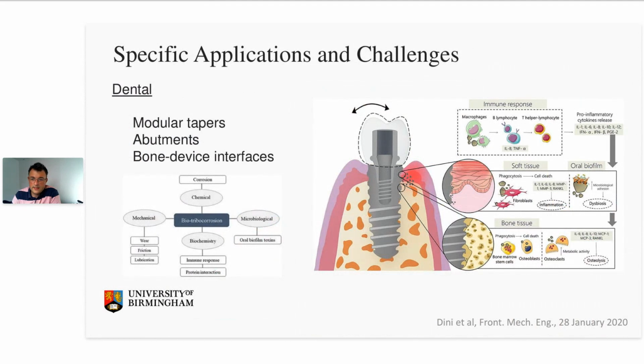A similar area is dental. Dental is a massive area, where you have these abutments, but ultimately you've got bone tissue, device tissue interfaces, device, and then device ceramic interactions. But the dental domain is particularly complicated by the fact that you've got more complex soft tissue structures which are more sensitive to metal ion release. You've also got issues around staining of tissues, which is not so much of an issue for things like hips. So it's quite common with titanium hips that you'll see staining of tissue, but it doesn't cause a problem. But also things like bacteria and the oral biology, biofilm formation, also contribute to ultimately threatening performance of these devices.